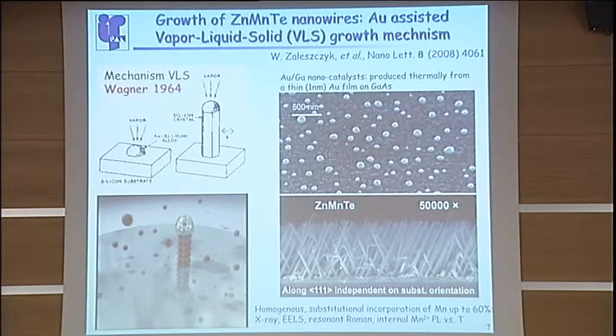And that was not at all obvious, that manganese will build into the nanowire in this kind of growth, but we have demonstrated it by various experiments. So this is the scanning electron microscopy of a forest of the nanowires. They always grow along 111B, typically the preferential direction. So independent of the substrate you use, the only thing which changes is the angle from the substrate.